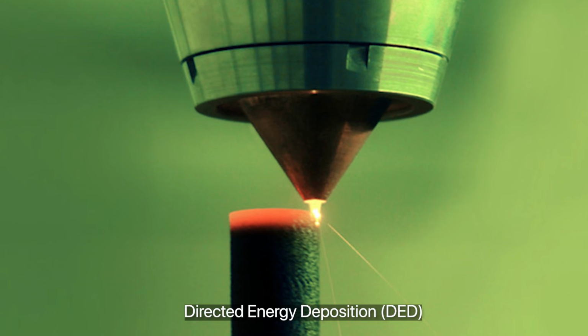Then the next process is directed energy deposition, which is one of the simplest processes. In powder bed fusion as well as the electron beam based process, you need a powder bed. That means you need a large amount of powder to just start printing something, something in tens of kgs of powder. Now let's say you have very little powder and your powder is super expensive. Those are not very efficient processes that you would like to go to. So that's why we have directed energy deposition.